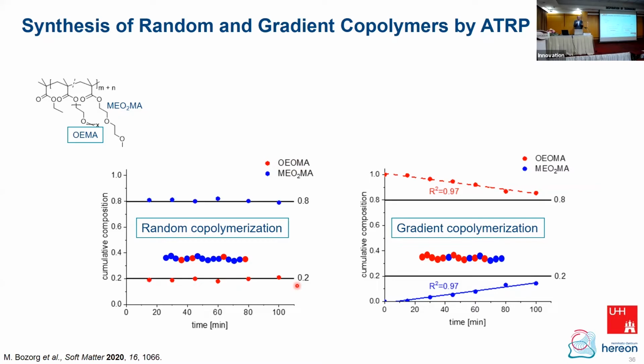So she increased one of the monomers as a function of time, basically. And by this, you somehow shift the actual composition of the monomer feed. That means you gradually change the composition generated in the growing polymer chain. So you can do that in a living polymerization only. And it really works. You see here the conversion plots, where you see the composition as a function of time, gradually changing for the two monomers, and you generate exactly such a gradient copolymer.